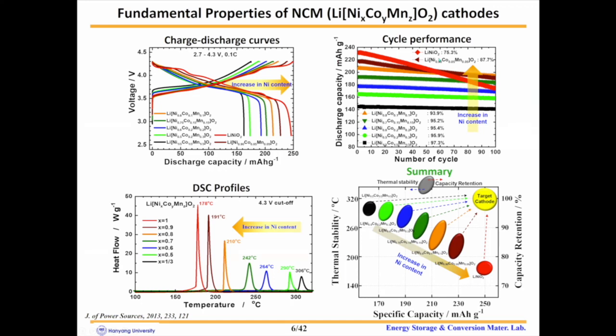On the other hand, the cycling performance decreases with increasing nickel content. And as you can see from the DSC profiles, with increasing nickel content, exothermic peaks shifted to lower temperature with higher heat generation. This is the summary of this part. With increasing the specific capacity by raising nickel content from one-third to 100%, thermal stability and capacity retention accordingly decreased.